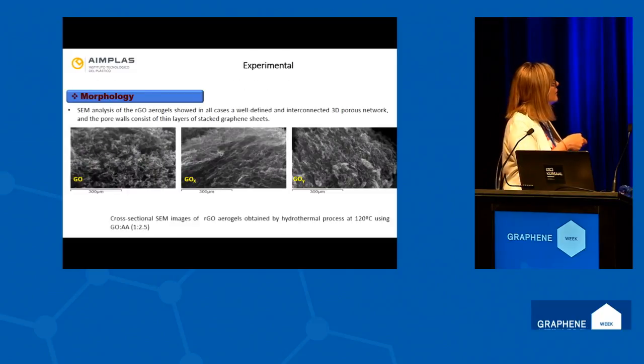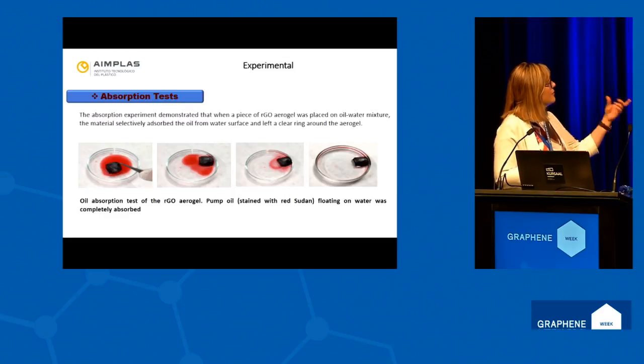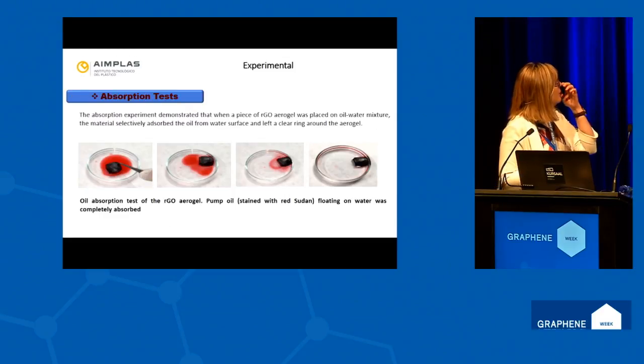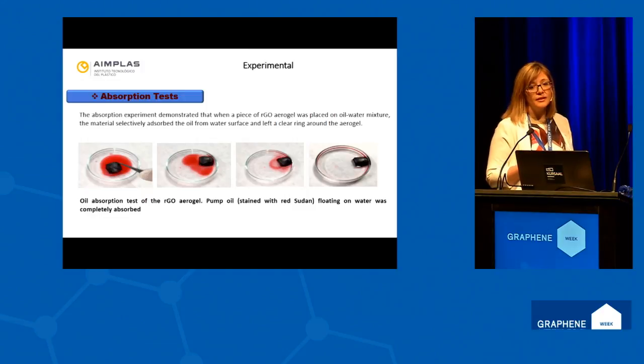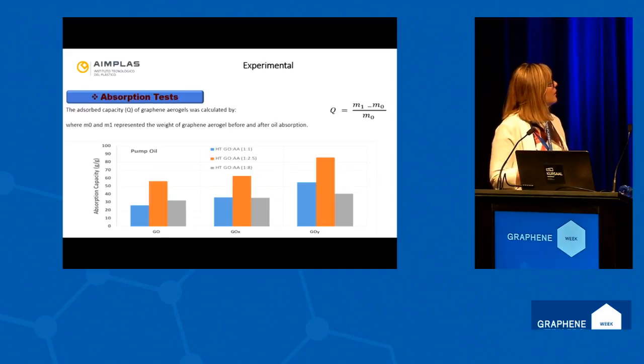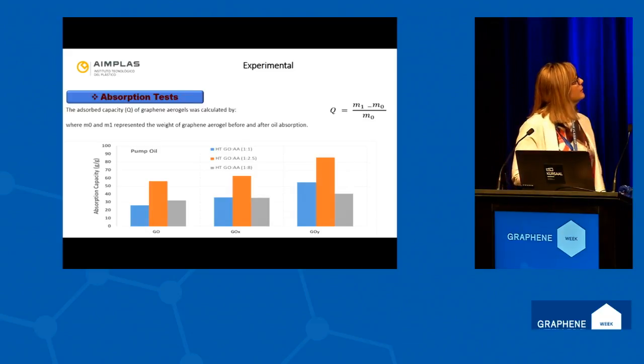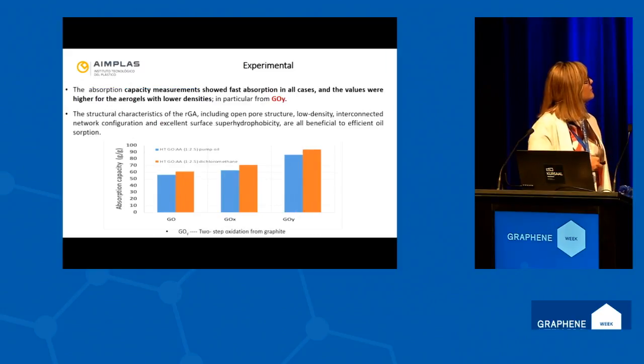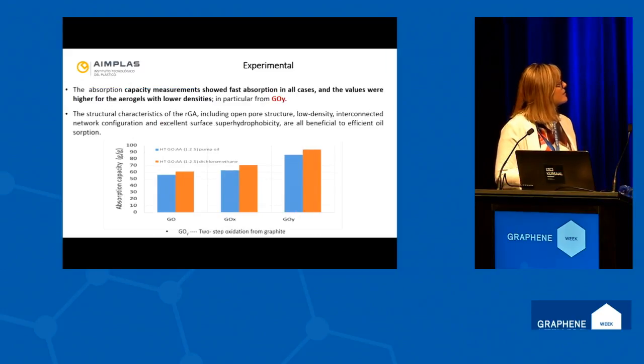Well, this is an image, SEM images, where you can see the porosity of the structure. And this is better because you can see that really the aerogel is working with the oil. It's absorbing the oil, separating it from the water. And this is, well, the absorption capacity. Our best results up to now are with graphene oxide. You have here the results.